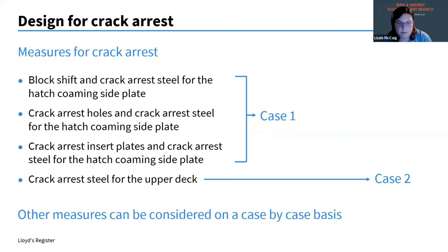So you can do something called block shift, where instead of having the weld for your hatch coaming in line with the weld of your upper deck, which is then in line with your side shell, you can offset these. So if you have a weld that's initiated in your hatch coaming butt weld, it will then get halted by the plate instead of going into the weld seam of the upper deck. You can also drill crack arrest holes, and again, these will halt a crack in the weld. And you could also use crack arrest insert plates, which will also do the same thing.